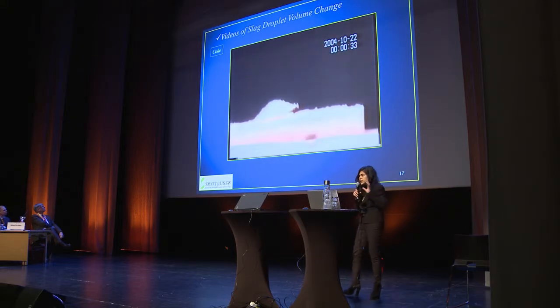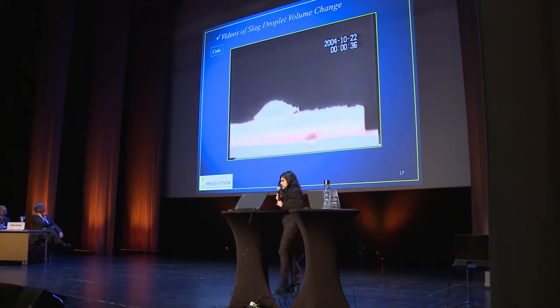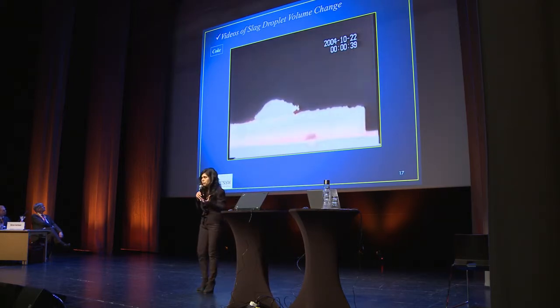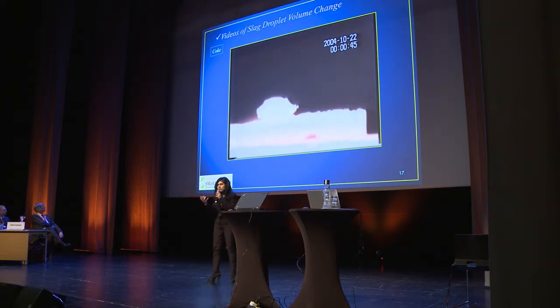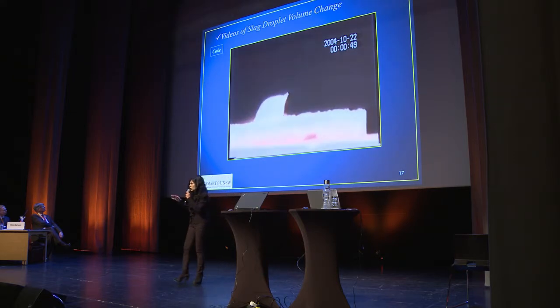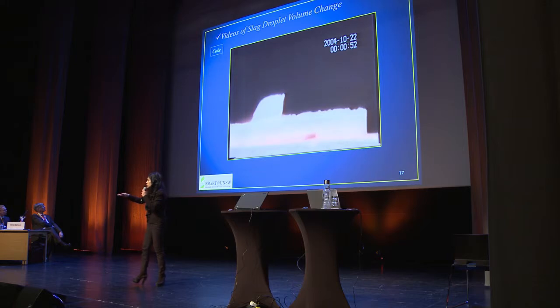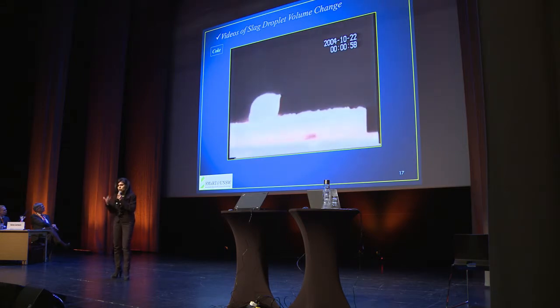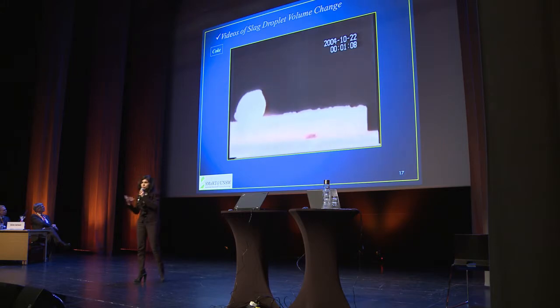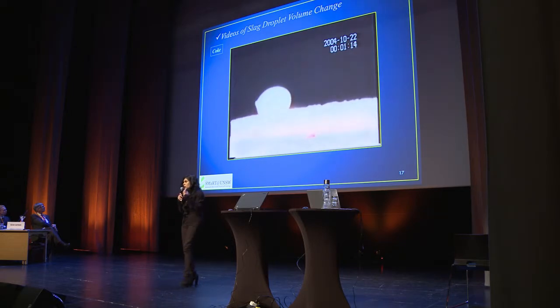What you're looking at here is straight down a high temperature furnace. You've got basically slag that's from EAF, about 30% iron oxide. It's sitting on a substrate which is effectively 100% coke, so traditional coke, and we've done our experiments where we always start off with the reference of what the traditional material that a company is using, for instance. So what you'll see here, of course, is as the reaction starts to happen at high temperatures of 1550 degrees Celsius, iron oxide reacts with that carbon, and of course, as you would expect, the reduction of FeO begins, and you've then got the ability of that slag to, for some period of time, sustain that foaming, although not too long.